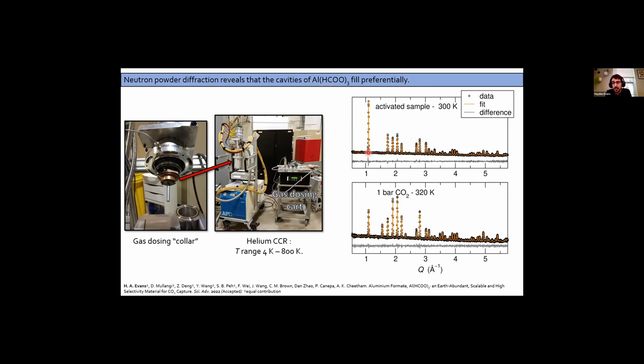So Craig was saying you might get a little bit of an increase in the background. You can see the slope. The sloping background is a byproduct of this protiated sample. But you can see, because it's so crystalline and it's such a beautiful sample to work with, there's no problems with doing the diffraction analysis, right? And you even get some contrast because of the negative scattering length from the hydrogen.